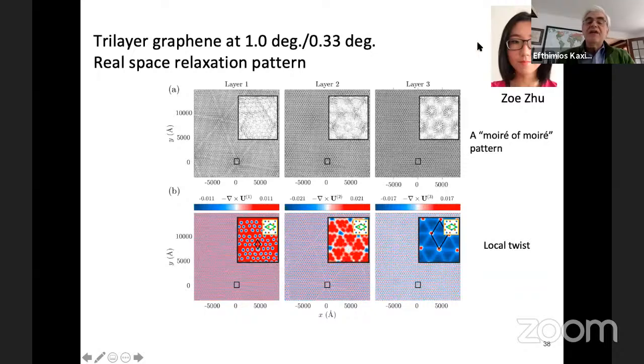So this is another very good student that I'm working with at the moment, Zoe Zhu. And she produced these relaxation patterns. This is layer one, layer two, and layer three. Layer two is in the middle. And you see that layer two is a very weak pattern, but layer one and layer three have stronger patterns of relaxation. And you can calculate also the local twist. So this is what the bottom pictures show you.